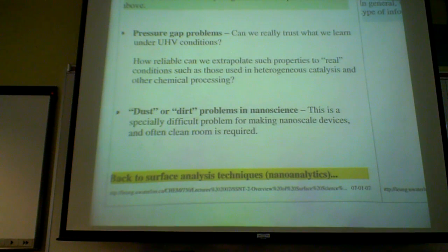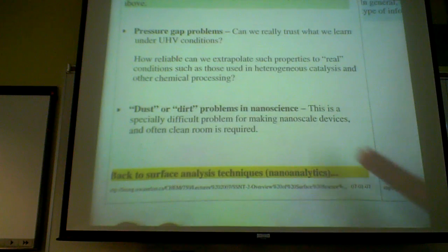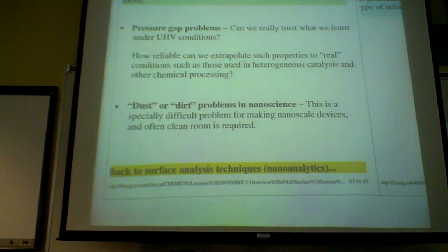So then people would say, let's clean off this carbon and oxide, and then you put an artificially controlled amount of carbon and oxide on your nanoparticle, and then you can study the overall effect of this dirt on your surface. And it has been found, in some cases, your dirt is very useful. Your dirt, in fact, is the one that promotes the reaction, could act as catalyst. So the amount of dirt on your surface could be an important component of your nano object.